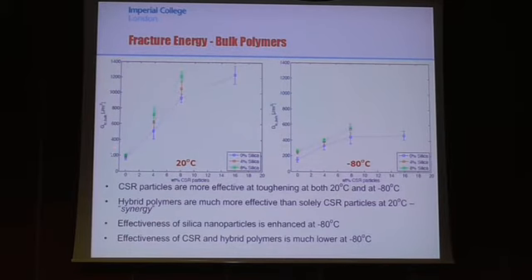When we add the CSR particles up to 16 weight%, we see that we get an increase of almost a tenfold increase at 16 weight%. And there seems to be a reasonably linear trend, at least up to 8%. When we add in CSRs and silica together, we see that actually the silica tends to enhance the toughenability of the CSR. So the hybrid materials have some synergy associated with them at 20 degrees. So the difference between this value and this value is about 350 to 400 joules per meter squared, whereas just with the silica on its own, we only get a difference of about 40. So by adding the two together, we're actually seeing a synergistic effect.